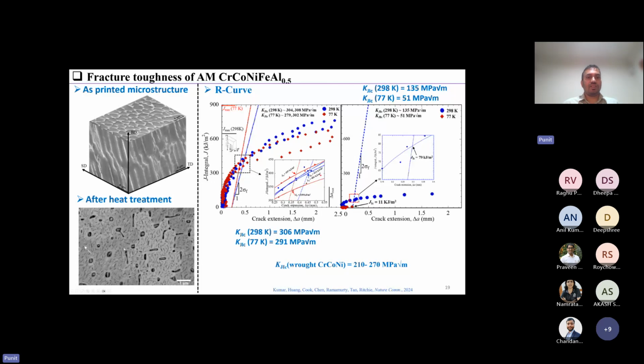And when we do the fracture toughness test on this microstructure instead of the honeycomb microstructure, we see the fracture resistance at room temperature drops significantly. You can see the difference in the R curve, and fracture toughness is almost less than half of what we see at room temperature in the honeycomb microstructure. And at cryogenic temperature, fracture toughness is reduced even more and is almost 6 times less. And after a certain amount of crack growth, about 0.2 to 0.3, we see the material fractures by unstable crack growth. So the fracture resistance is significantly lower.